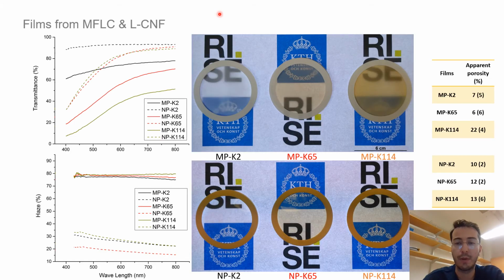After that I have prepared films. You can see micropaper films when I had the whole fraction of MFLC and when I had just the supernatant, small fibrils. I prepared the films with vacuum filtration and oven drying at 50 degrees overnight. You can see the optical transmittance and optical haze of the films.